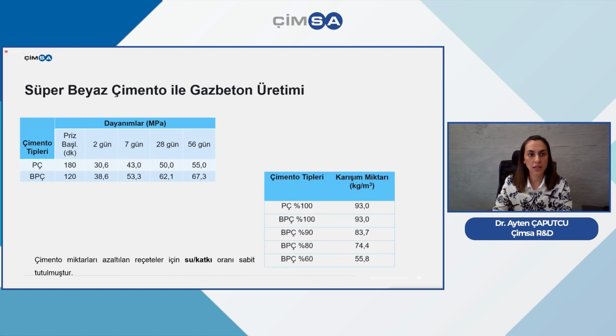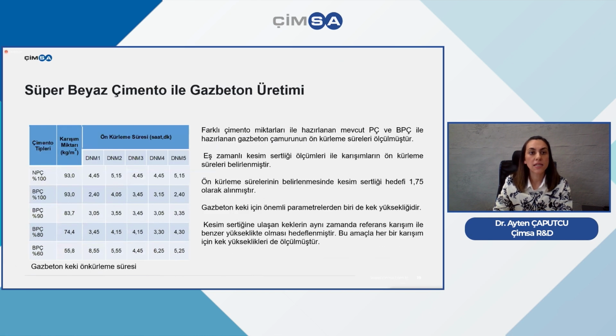As you can see here, the first differences between Portland cement and white cement. And here 60 minutes is the difference between the starting time, and we know that 60 minutes is quite an important duration for our sector. We see that white cement is actually more resistant. So in our study, we replaced Portland cement with white cement, but we kept the ratios constant.